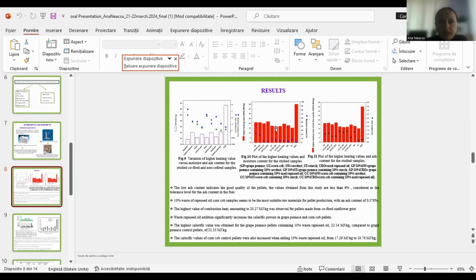We present our results. We plotted the higher heating values obtained versus moisture and ash content. The ash quantity was calculated from the difference of the bomb crucible masses before and after combustion. The moisture content was expressed as the water proportion contained in the ground biomass. It is known that moisture content is the most important factor that influences the calorific value of biomass. From the represented plots, it can be seen that the lower heating values of the studied biomass samples are caused by high moisture and ash contents.